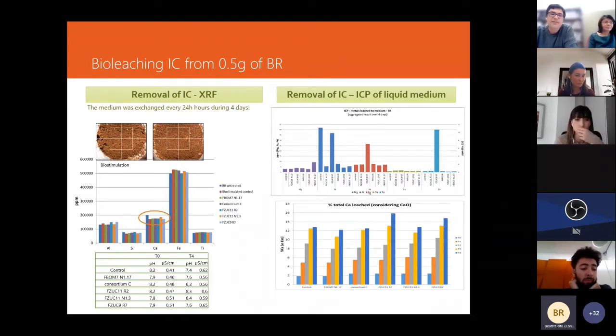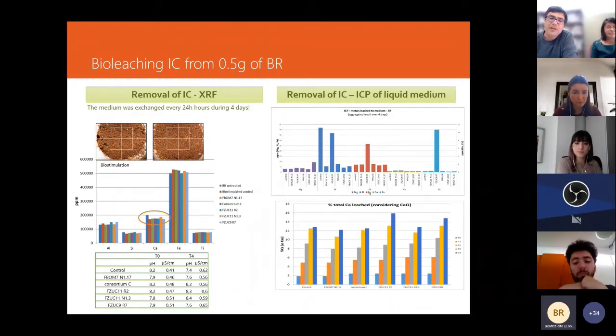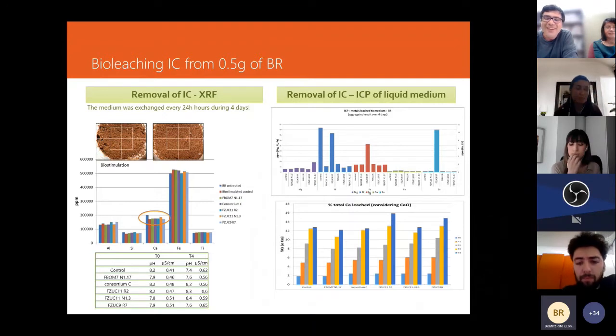What we can see is that the pH did not actually drop. There was no significant acidification. In fact, all the pHs at the end of the experiment were above 7. I must say that the bauxite residue has a pH of 13, which is quite a lot, but we started with a pH of about 8. Looking at the results of the XRF, we can see that some calcium disappeared when compared to the original residue, and the leaching of calcium was confirmed by colorimetric methods. We were not really happy with the leaching of other elements, but at least we had some calcium being leached. So next slide, please.